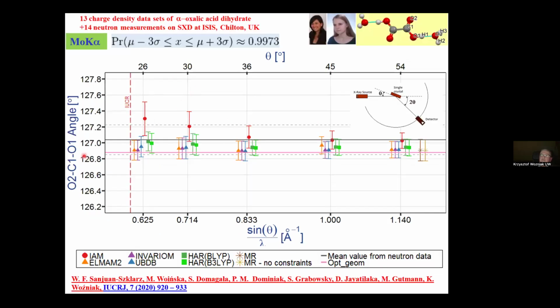And when we take a look at the valence angles, the dependencies are more or less the same. If IUCr would recommend higher resolution, which these days, since data collection is that fast, doesn't matter. I mean, it's only a small increase of data collection time. And we can see that Hirschfeld atom refinement, these are the green results, is really very stable over the whole resolution range, even for small resolution data. It is giving results very close to neutron diffraction.